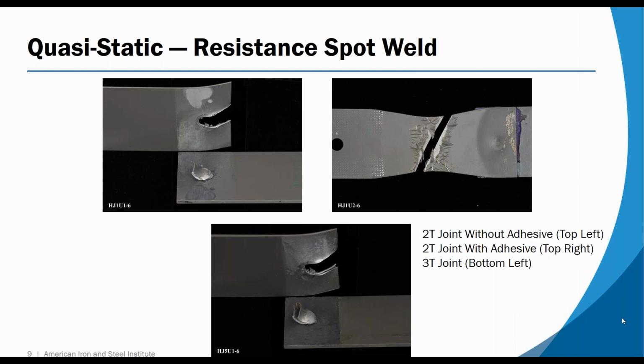The upper right is the same joint, but with a structural adhesive added. And you can see the failure mode there is moved into the top sheet because the combination of structural adhesive plus resistance spot weld was stronger than the top sheet was. And in the bottom, you see a 3 thickness joint with, again, a fairly classic weld nugget pull failure mode.